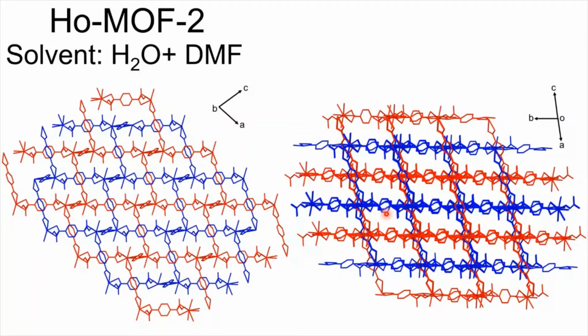This is called interpenetration of MOFs, and it is a very common problem, especially when you're trying to build these huge cages of huge pores, because the space is so big that it will allow another linker to go in there and start creating this MOF around the other MOF.